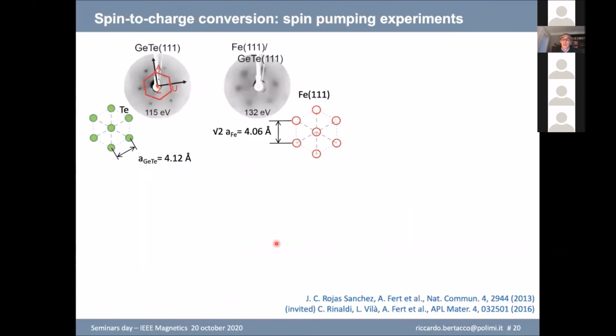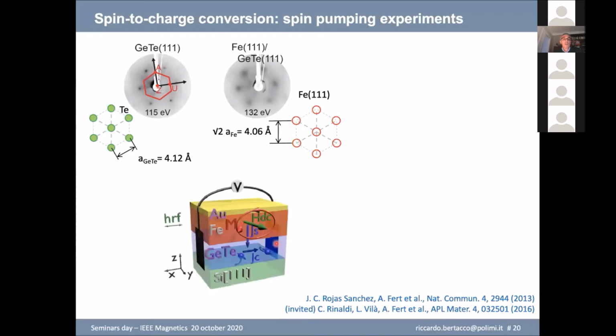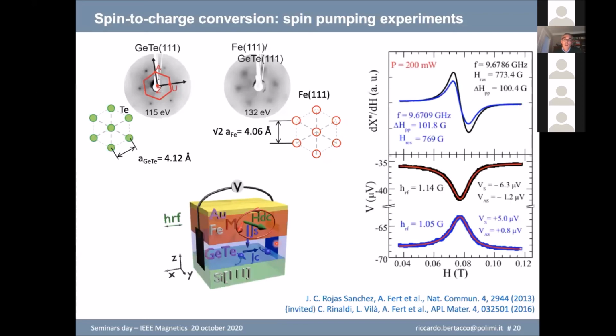So the first experiments we carried out a few years ago were experimental spin-to-charge conversion by spin pumping experiments in collaboration with Fert and Laurent Vila. At that time, we produced this iron germanium telluride heterostructure, which is fully epitaxial, and we measured by spin pumping that there is really a spin-to-charge conversion. The idea of this experiment here is quite simple. You have your ferromagnetic layer, you apply this DC field HDC pointing in this direction, the green arrow here, and then you apply a radio frequency field in this direction.